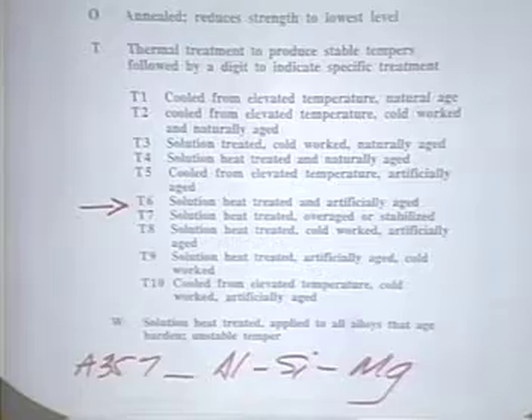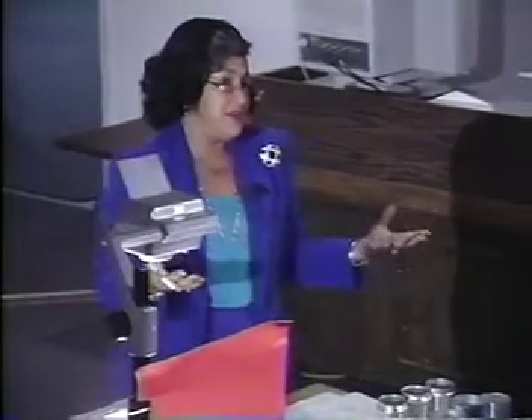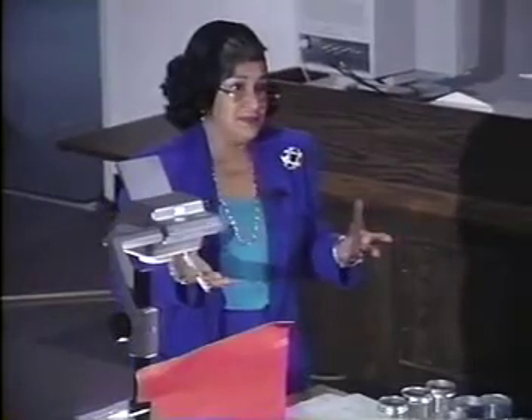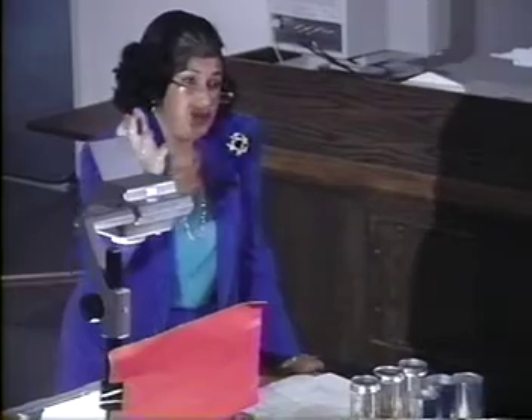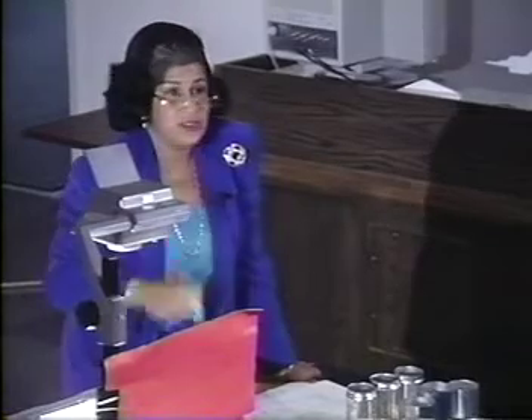One way that we can increase the solubility is to do the same thing when you make tea at home. You heat it up and you add the sugar when it's hot. So we heat the metal up and we increase the solubility. This is in the solid state, however. These are solid treatments. We're not remelting it. We've already shaped the part. We heat it up. But even in the solid state, as the temperature goes up, atoms can add themselves to the lattice of aluminum and form a solid solution.